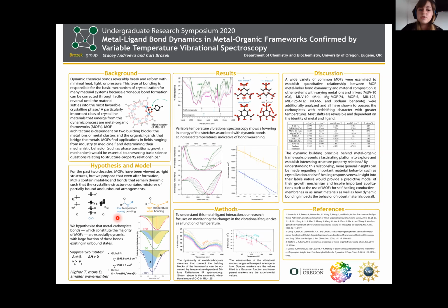So the main goal was to identify structural changes within the system caused by applying stress onto the system in the form of heat, and more importantly, establish a quantitative model for this phenomenon, which we call the equilibrium model and just showed here. This model derives from the equation that relates equilibrium and temperature, and we assume A to be a completely associated state, which is more populated at lower temperatures, and the higher in temperature you go, the more you populate the dissociated state B.